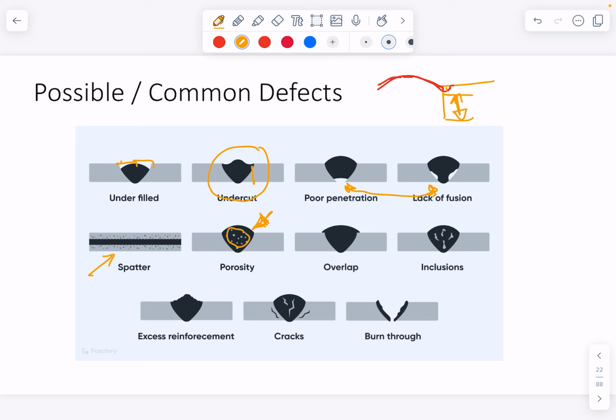any MIG or stick type process, you're going to get some spatter, and you'll normally spray the job with a spatter guard to enable those little bits of rogue metal not to stick. But again, you've got imperfections sitting on a surface that might cause some stress concentrations. Overlap, stress concentration. This is probably going to be a fairly cold joint there, perhaps. So it may cause all sorts of other problems. Inclusions, if you pick up a stick welder, anyone fairly new to stick welding will end up with inclusions galore in their welds. And of course, that's just a place for stress concentrations to start.